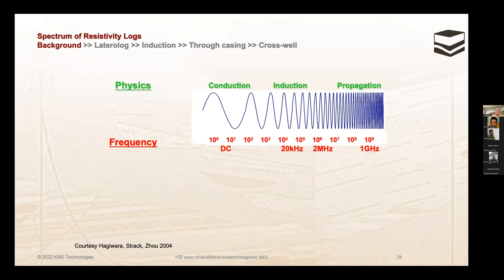Now, we have many, many logging tools to measure this. What we measure with the low frequency is resistivity. With the inductive tools, we are measuring conductivity. It's the inverse of resistivity, but we are measuring a volume effect, whereas with resistivity, we are measuring a direct flow. And dielectric constant is a propagation effect. So when we look at dielectric constant that responds also to the conductivity, we are looking at the propagation effect.